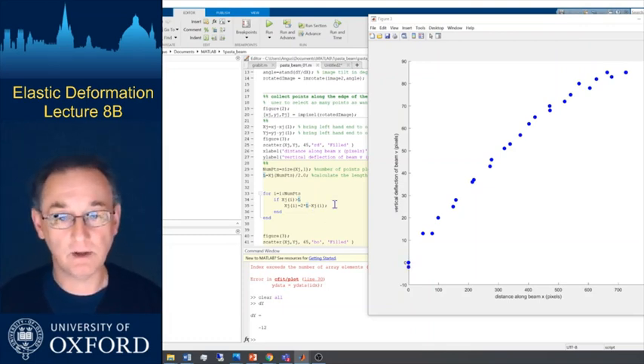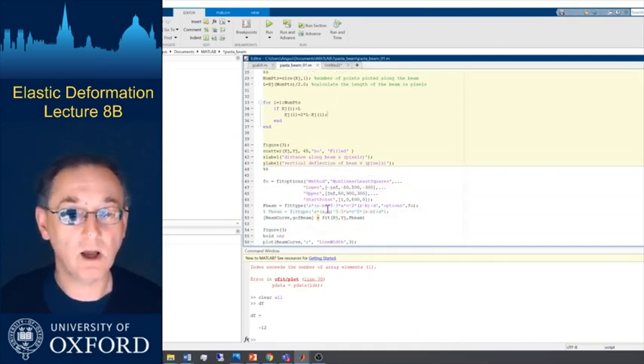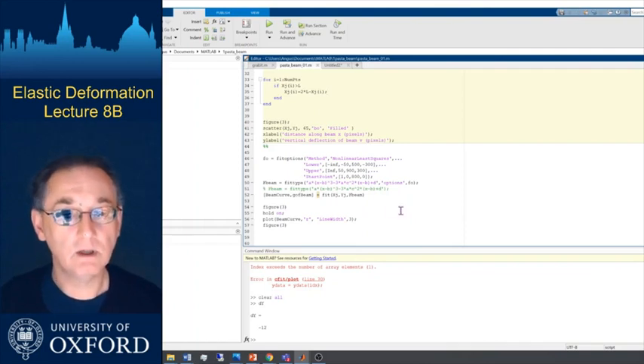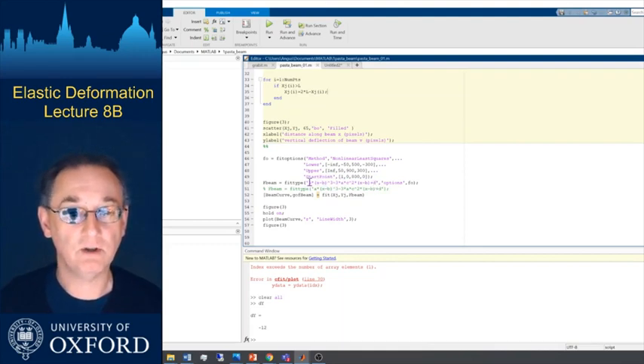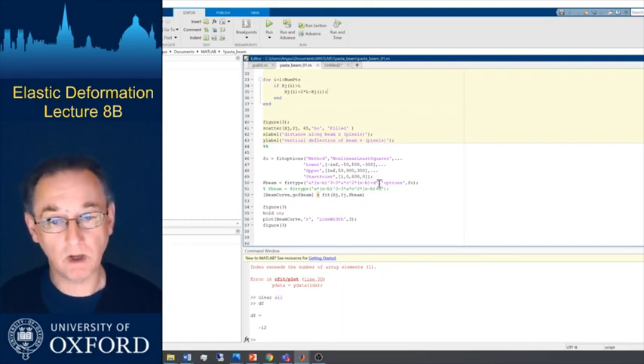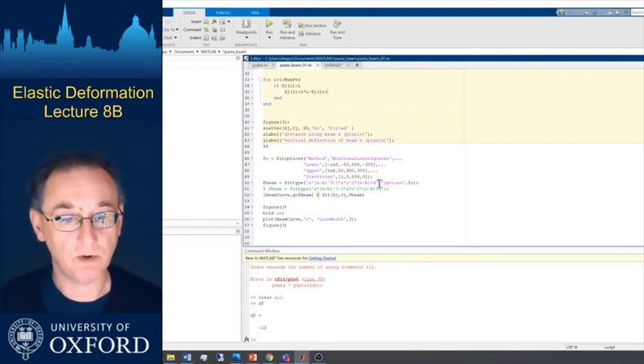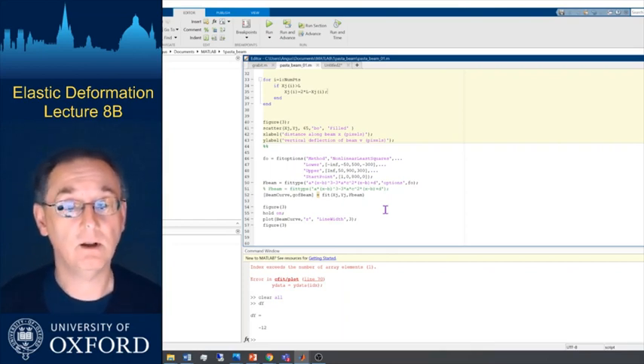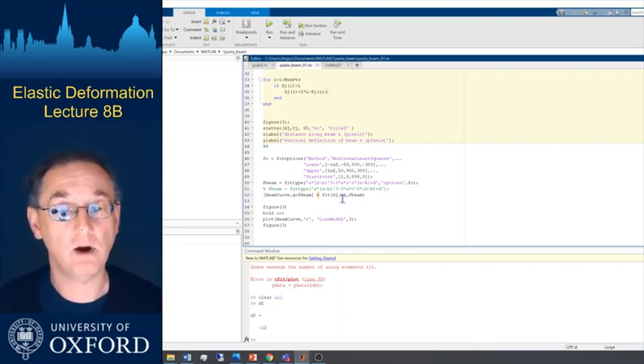So the next thing to do then would be to fit that to our function. And so in here is the function that we had for the displacements in our beam that's in the PowerPoint that we've just talked through. And so the X's in here are the position across the beam. The A, B, C, and D are parameters that I need to fit to establish what they are numerically. You'll see how I've set this up. There's a term in X cubed with a constant in front of it. I'm just allowing there to be an offset in the origin in the X position. I might not have correctly located that first point for the beam. So that's why there's an offset here, hoping that small, it means I haven't made too big an error.